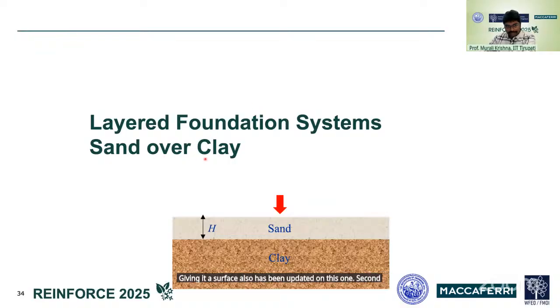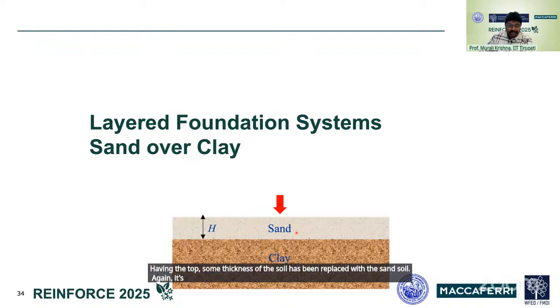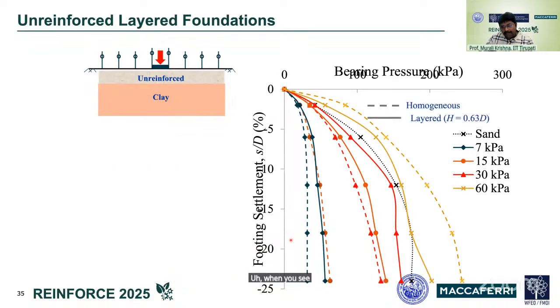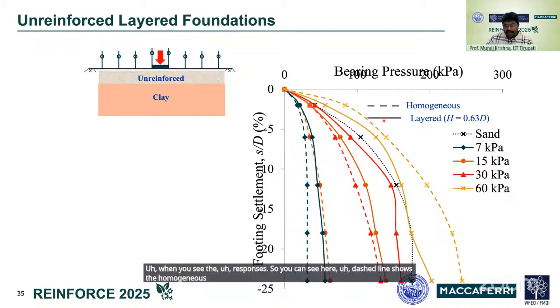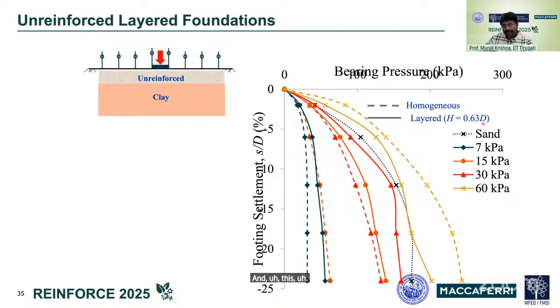The second configuration has some thickness of the top soil replaced with sand. Again, it's a layered configuration, but unreinforced. There is no reinforcement in this case. When you see the responses, the dashed line shows the homogeneous soil case, and the solid line shows the layered soil with the sand having 0.63 times D as the thickness. So in all the curves, we can see there is a significant improvement in the capacity when we replace the topsoil with the unreinforced sand.